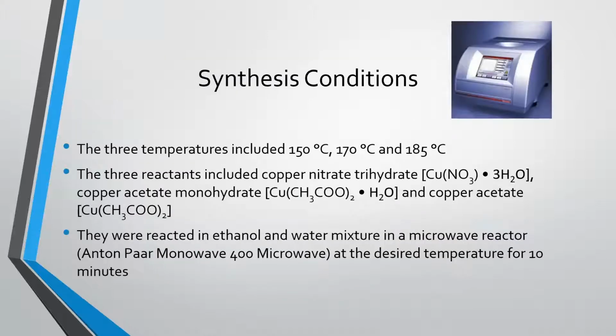For our synthesis conditions, 3 temperatures were observed, including 150, 170, and 185 degrees for 3 samples of copper acetate monohydrate. Then we observed 3 different reactants, all at 170 degrees. These reactants were copper nitrate trihydrate, copper acetate monohydrate, and copper acetate anhydrous. They were reacted in a 50-50 ethanol and water mixture in a microwave reactor at their specific temperature for around 10 minutes.